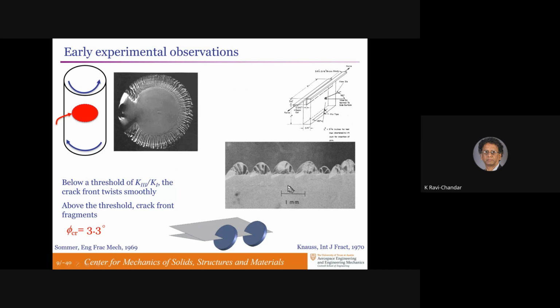Knauss did a pure mode 3 experiment. You cut a crack into a long, thin sheet and shear it, just like the picture of the rock formation that I showed in the very beginning. And the crack is under mode 3 completely. And it spawns daughter cracks. Instead of the parent crack moving continuously out, it pops out. It's independent fractures nucleated at some separation, yet to be determined what controls that. So basically, this is what happens. The parent crack is shaded gray. The daughter cracks that spawn out from that are those angled Pac-Man shaped objects.